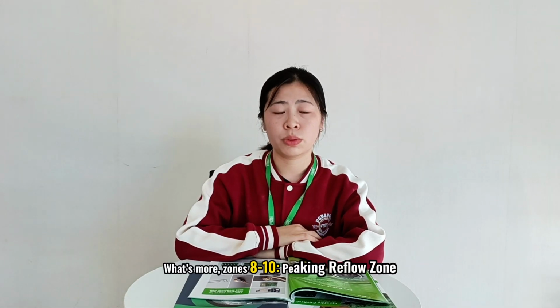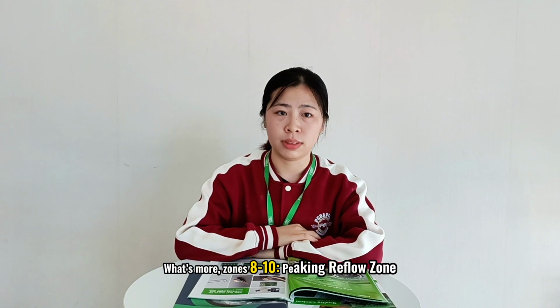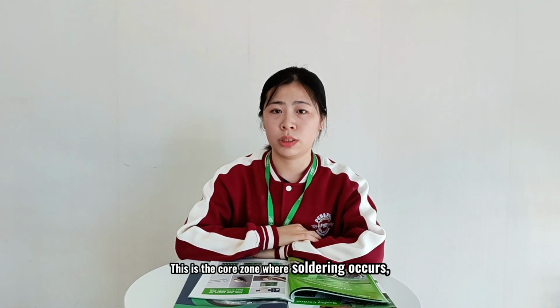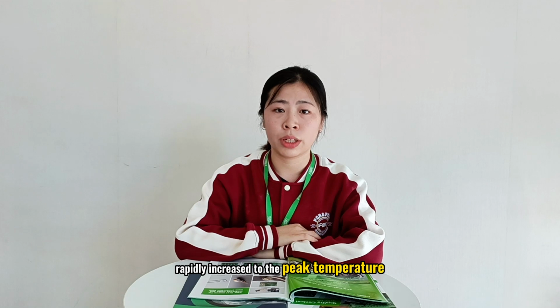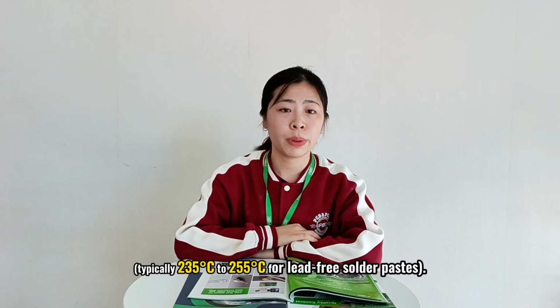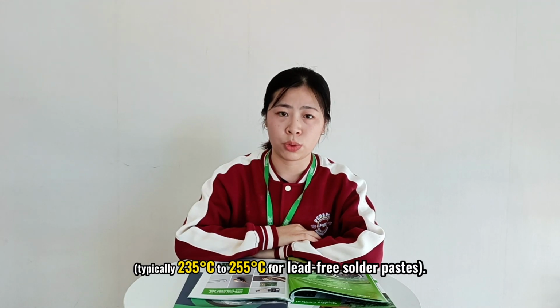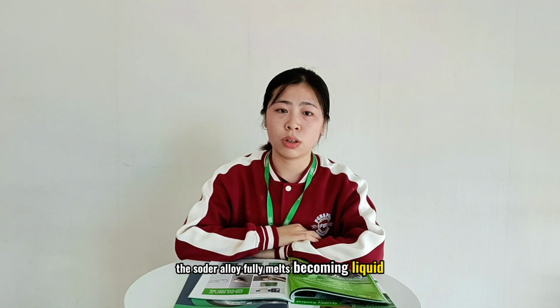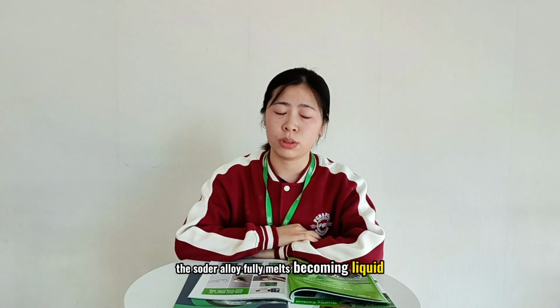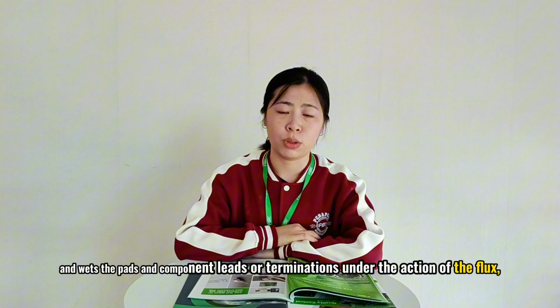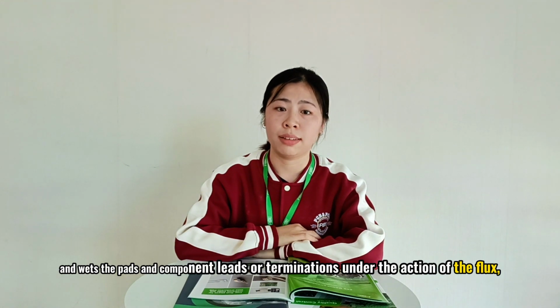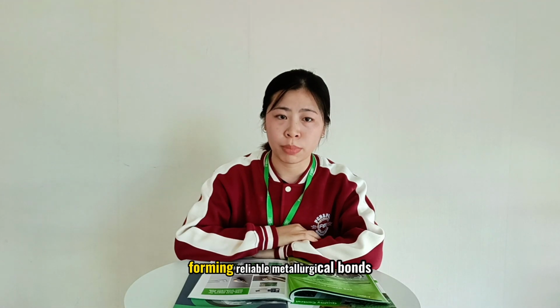What's more, zones 8 to 10, the peaking reflow zone. This is the core zone where soldering occurs. The temperature rapidly increases to the peak temperature, typically 235 degrees to 255 degrees for lead-free solder pastes. The solder alloy fully melts, becomes liquid, and wets the pads and component leads or terminations under the action of the flux, forming reliable metallurgical bonds.